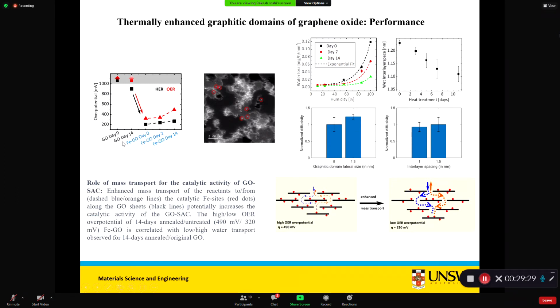And then we see that when we do it, it improves a little bit. The catalyst properties of graphene oxide improve a little bit when you anneal the samples, due to conductivity change. But then when we introduce some single atoms into graphene oxide, like we used Fe in this case, the performance is a huge change. You see here, from here to here, this is the best performance. And as we see here, when you have no iron in graphene oxide, the performance is improved because of conductivity, because the conductivity is higher now because of the high graphitic domain. But when we introduce Fe, the mechanism changes. Now Fe plays a crucial role.